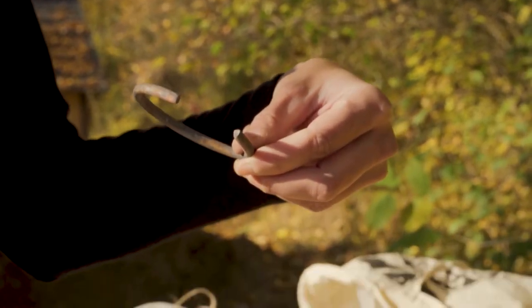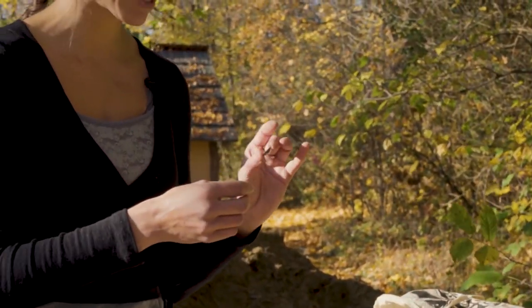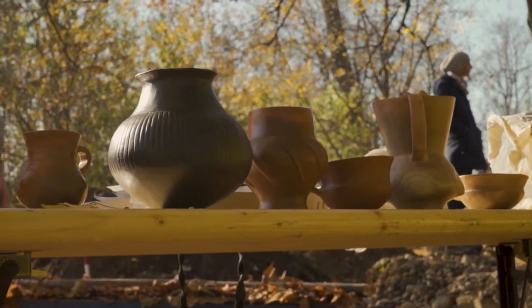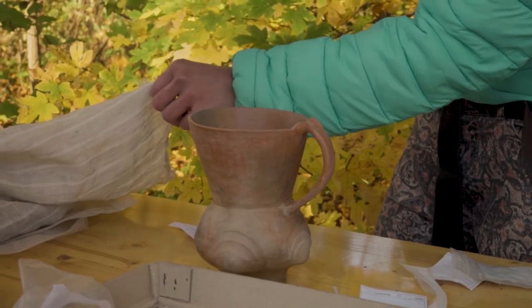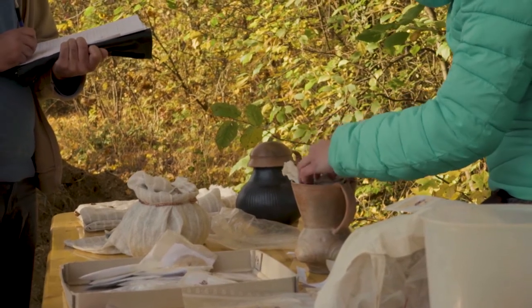For this purpose, we cut several of the objects in half with the intention of keeping some of the halves and burying the others, so we can then make a direct comparison of how they change in the soil. We are particularly interested in the structure of copper and tin in the bronzes, as these components react in different ways. When burned, the tin slowly diffuses outwards. This is also what happens when stored in the ground. It is therefore interesting to see how exactly the subsequent storage in the soil additionally influences the process.